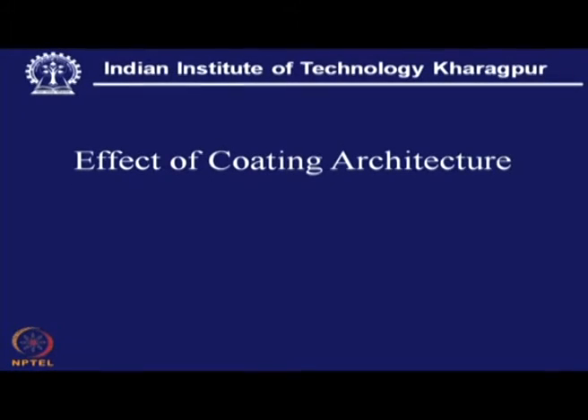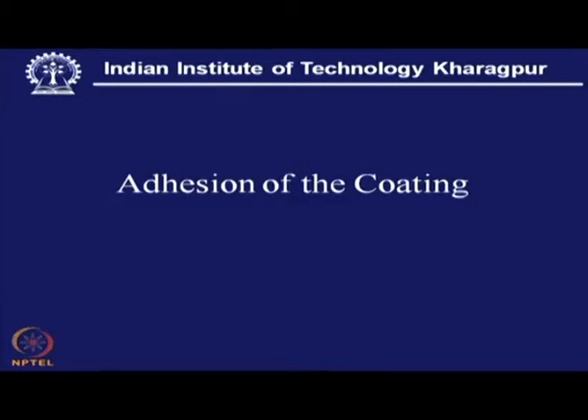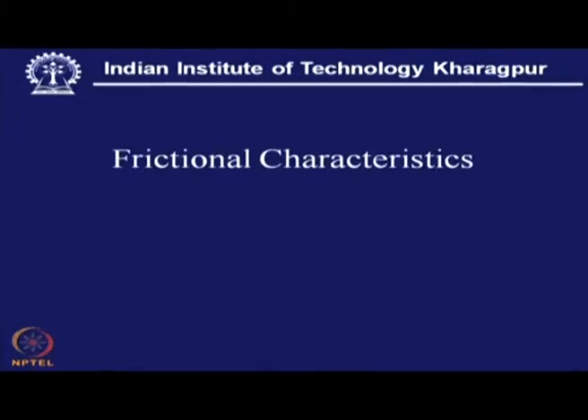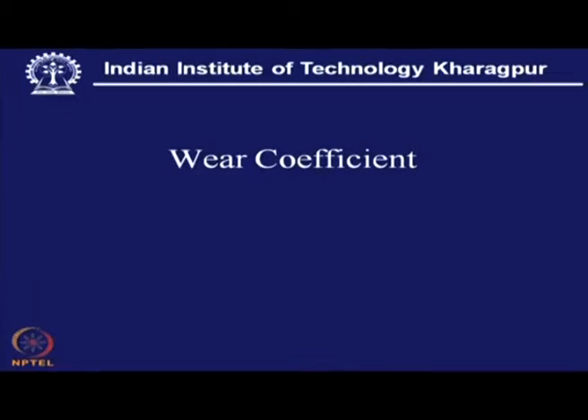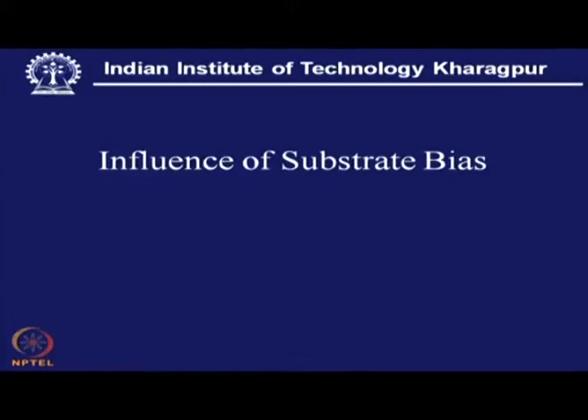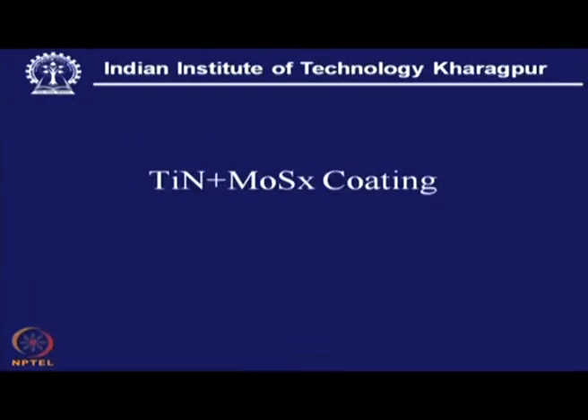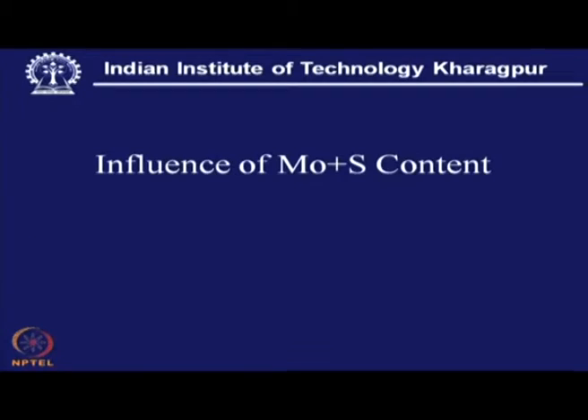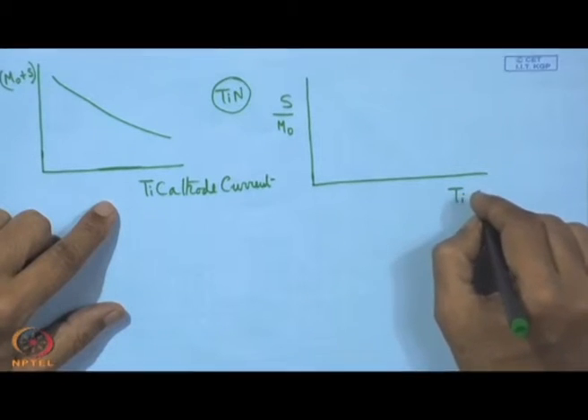So, what we have seen so far is the effect of coating architecture that we have just discussed. With this coating architecture, we found that the MoSx plus titanium nitride coating architecture gives the best overall performance, considering adhesion, hardness, frictional characteristic and wear coefficient. So, considering all this, we saw that this is the best overall performance. Now, what we can find here is the TiN-MoSx coating, the influence of Mo and S content. Here also it is the Ti cathode current.